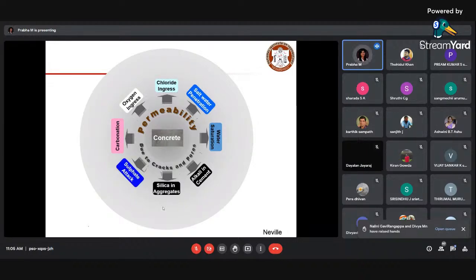In general, your concrete has some amount of alkali in cement and silica in aggregates, and depending on the exposure with respect to sulfate environment, or if the sulfate already in your concrete is not reacting when it has to react, then over time—especially during steam curing, when the temperature is above 80 degrees Celsius—you are basically suppressing the sulfate reaction in the initial stage, and that is going to react at a later stage and result in delayed ettringite formation.